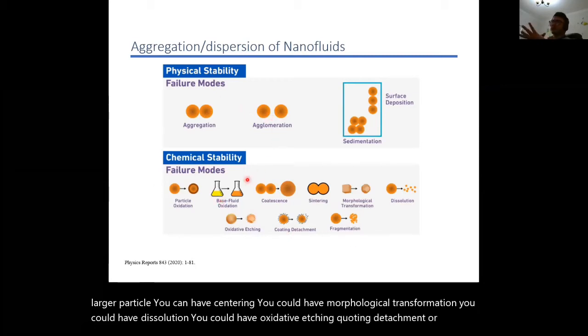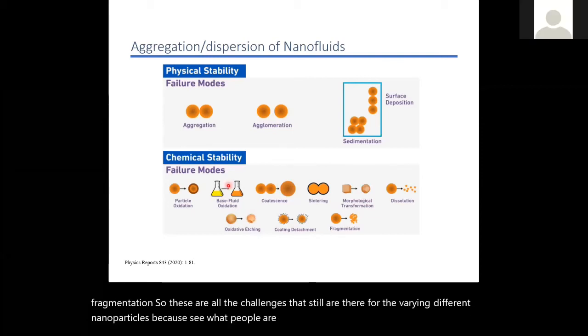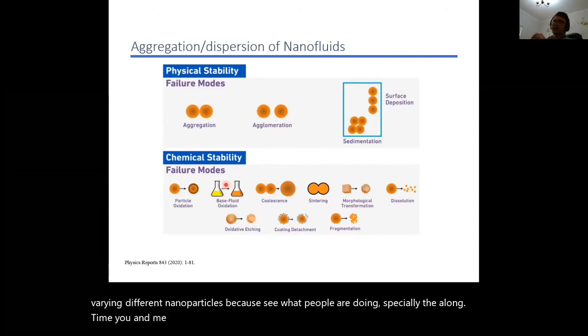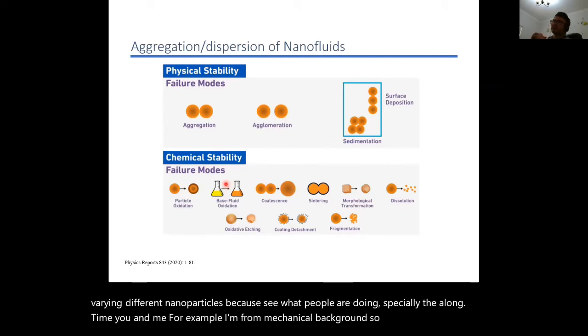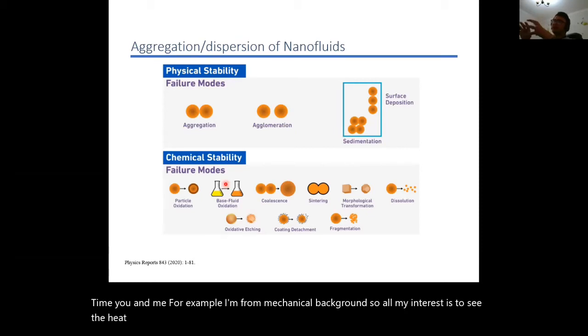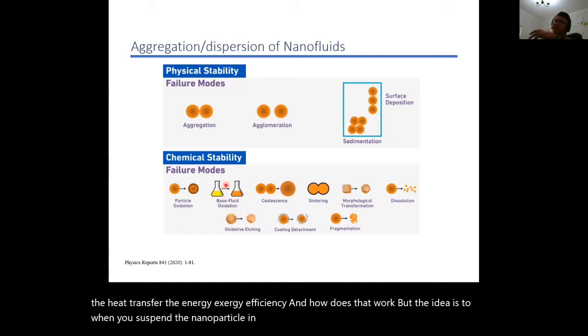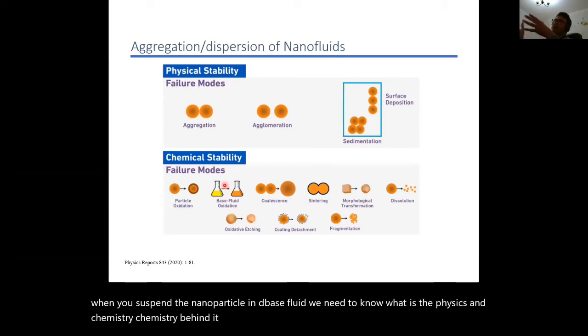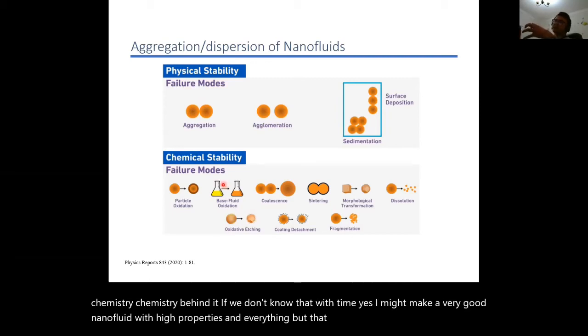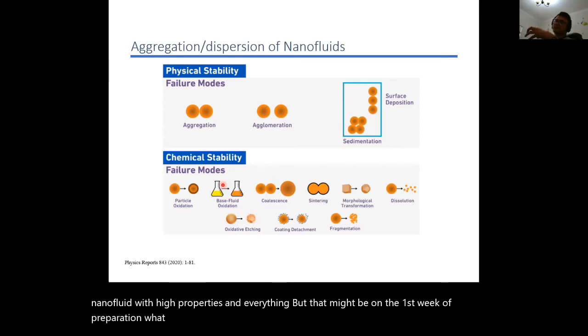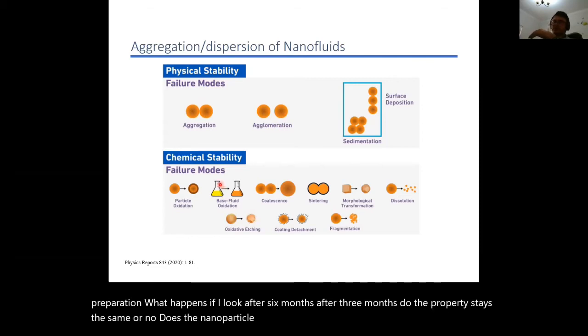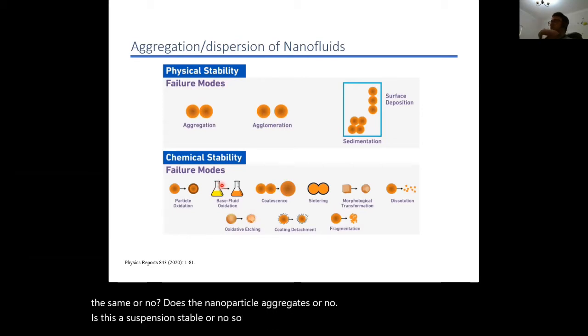So these are all the challenges that still are there for the different nanoparticles. Because see what people are doing, especially for a long time, even me, for example, I'm from a mechanical background, so all my interest is to see the heat transfer, the energy, exergy efficiency, and how that works. But when you suspend the nanoparticle in the base fluid, we need to know the physics and chemistry behind it. If we don't know that, yes, I might make a very good nanofluid with high properties, but that might be only in the first week of preparation. What happens if I look after 3 months, after 6 months? Do the properties stay the same or not? Do the nanoparticles aggregate or not? Is this suspension stable or not? These are very important questions that the industry is interested in.